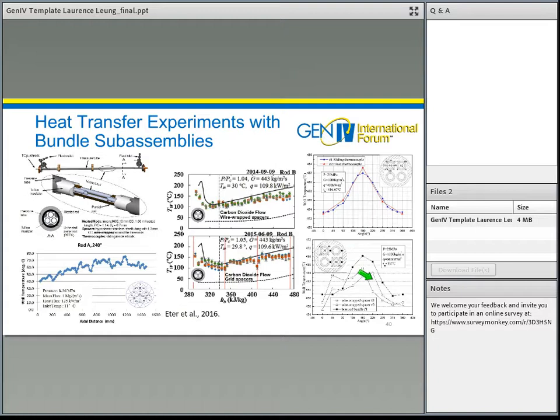In this figure, they compare the wall temperature measured between the rod with no spacer and the rod with spacer. In general, what we find is that the rod with spacer usually has a lower temperature in this area, as the open symbol shows, except when the spacer is located in that area. Because the rod itself is directly heated, the spacer also introduces heat to the system, and that's the reason you have a localized peak in the temperature. But in general, we find the spacer effect enhances the heat transfer.